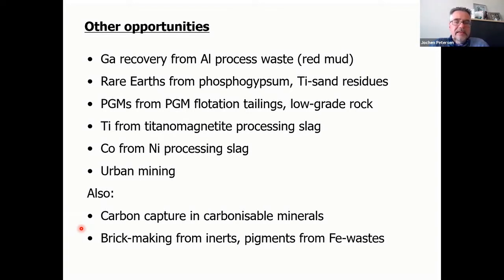Titanium from titanomagnetite. Titanomagnetite is mined for its vanadium content. That's a pyrometallurgical process, and the titanium reports to the slag. Cobalt from nickel processing slag. Similarly, the nickel was the attractive mineral phase in certain Southern African countries. The cobalt reported to the slag and was disposed of.